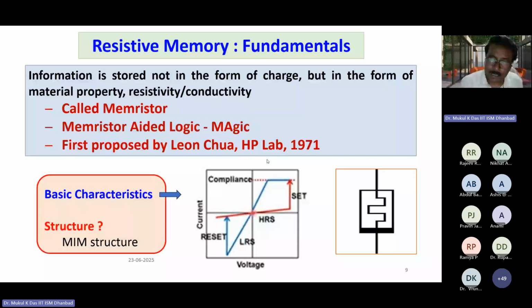So in that case, you can get a small amount of non-zero current. It depends again on the device. So ultimately, if you see, the tracing path and retracing path are not the same. That indicates there is a hysteresis. So some permanent change is there. This is called permanent change, and that is the origin of hysteresis in magnetic fields also. If you keep on increasing the magnetic field, any magnetizing material becomes magnetized, and if you gradually remove the magnetizing force, the magnetic property will not be removed completely, something remains. So that is called the hysteresis thing.